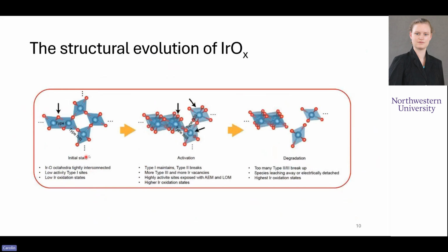So we have the initial state of our material here that is characterized by a mixture of type 1 and type 2 and 3, edge sharing and corner sharing octahedra. And the arrows here point to the active sites as calculated by DFT. And so initially, all those octahedra are really tightly interconnected. And we have this kind of lower activity type 1 active site and a fairly low iridium oxidation state.